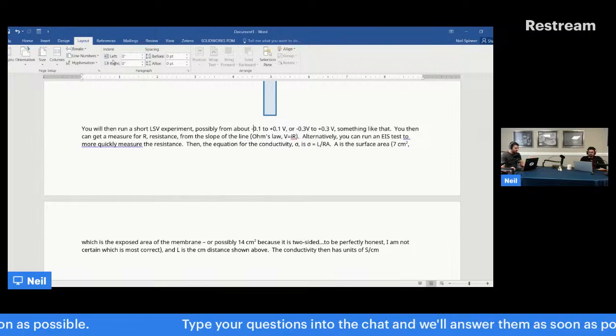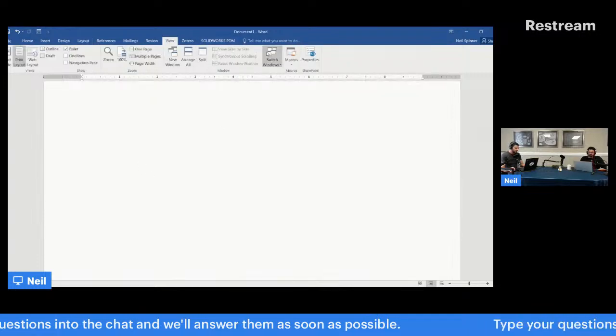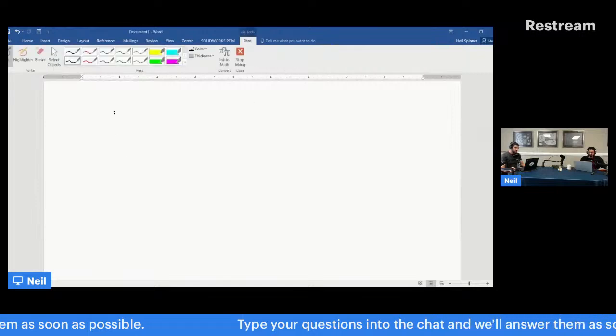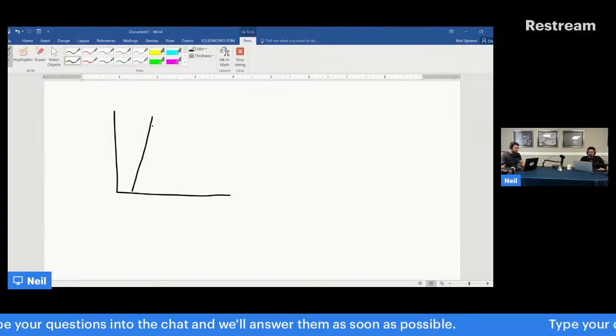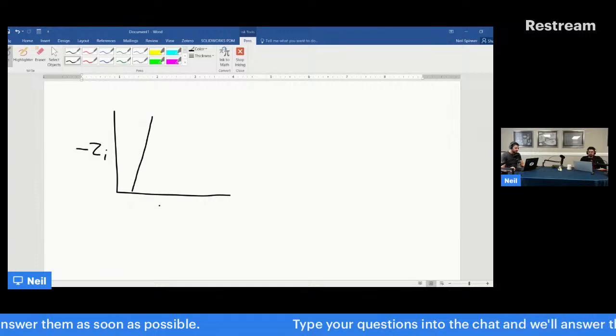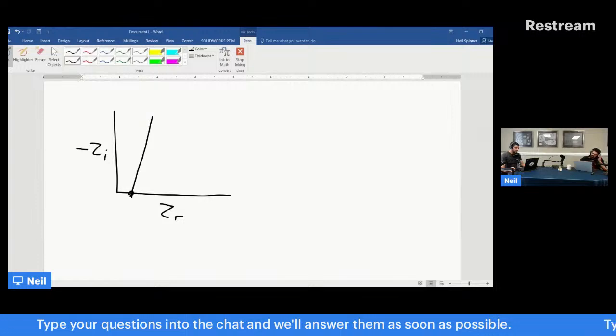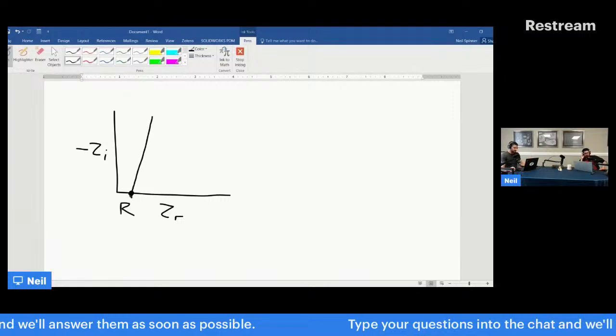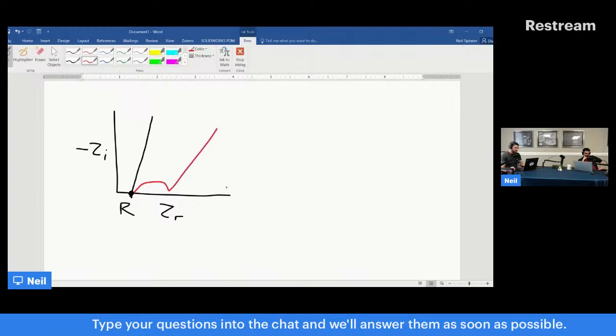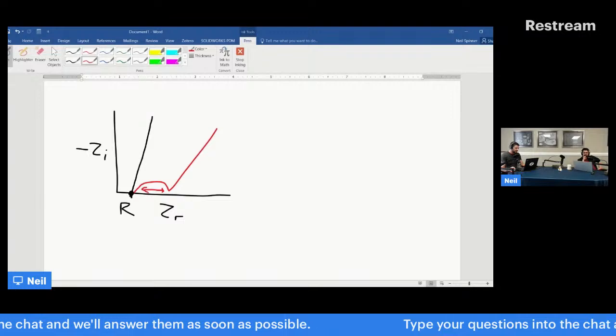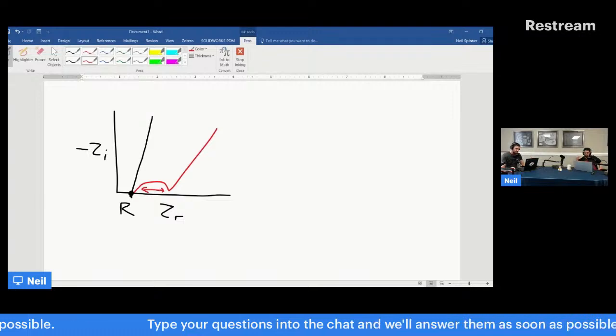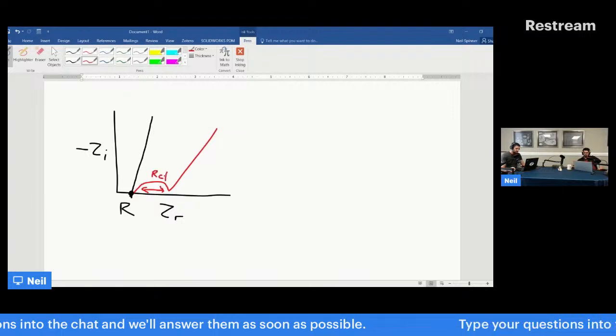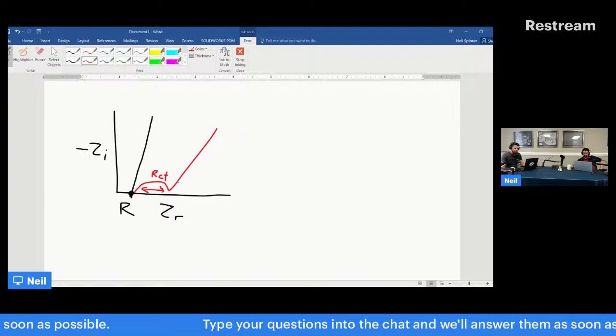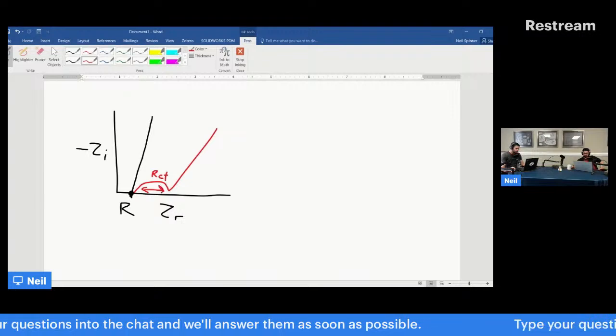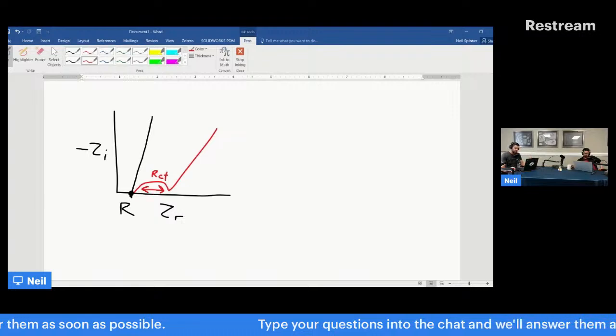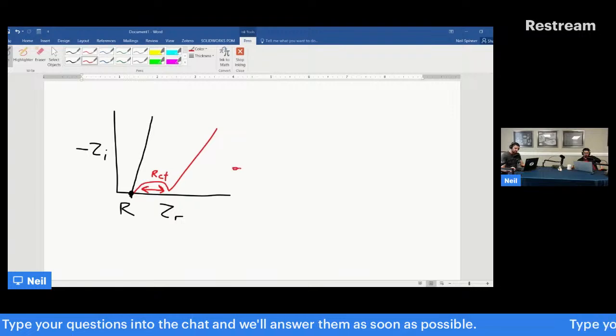I don't know, in theory, I guess that's the thing too. This is a tricky thing. If your impedance measurement in theory would just look like this for the Nyquist plot, minus Z imaginary and Z real, you're just looking for this point right here. That would be your R, just the intersection of the axis here. If somehow you have that, I don't know what this is, your RCT. Maybe that's what you're getting, and I don't know what that faradaic reaction is, or maybe this RCT here, if that's what you're getting for some reason, is the resistance of the membrane. I don't know if that's what you'd expect. I haven't done this experiment myself personally, I'm just speaking from a theoretical point of view here. But if that's what you get, the red curve, then maybe that is what you're looking for, and you would fit this with something like,